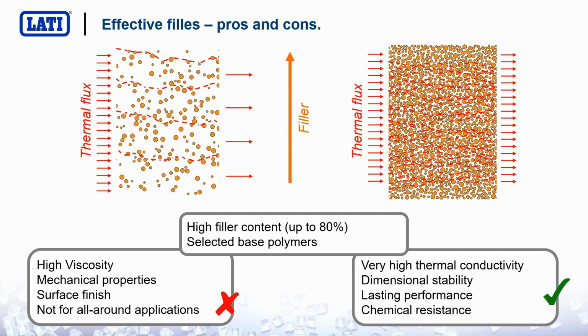First of all, you have a very high thermal conductivity, 100 times higher than ordinary plastics. Then you have a very good dimensional stability. Your injection molded part will stay flat and will respect the tolerances you have on your drawing because of the higher filler amount. The performance of these materials will last in time. So the thermal conductivity that we have been able to give to the plastic will not fade away in time. It will be constant in time. So you can actually design for a part working even in 20 years.